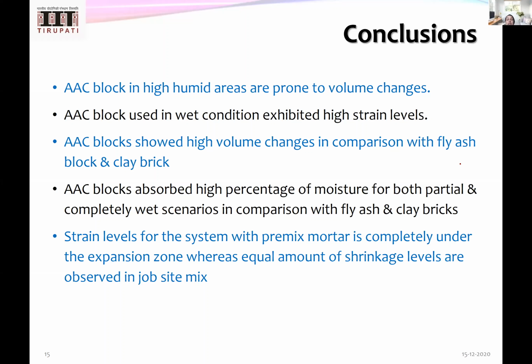And compared to fly ash and clay brick, there are very high volume changes. It is in the order of 700 to 800 microstrains in a partially wet scenario. But in a full wet scenario, it comes to around 1200 to 1400. So that's very high strain.